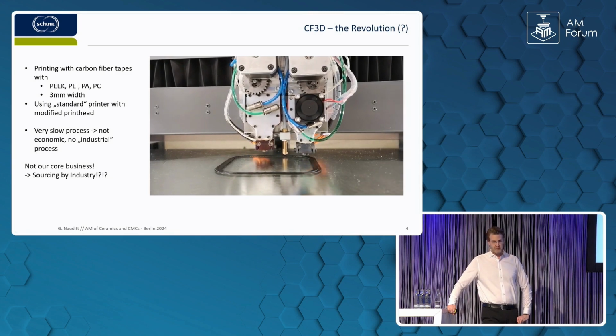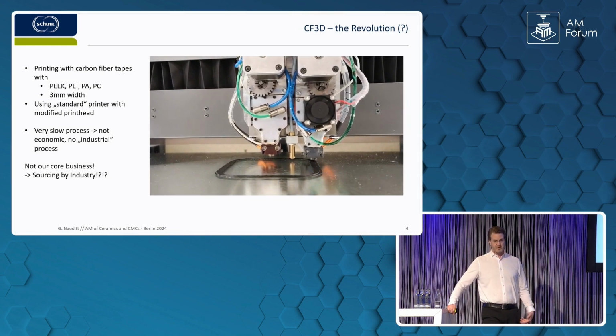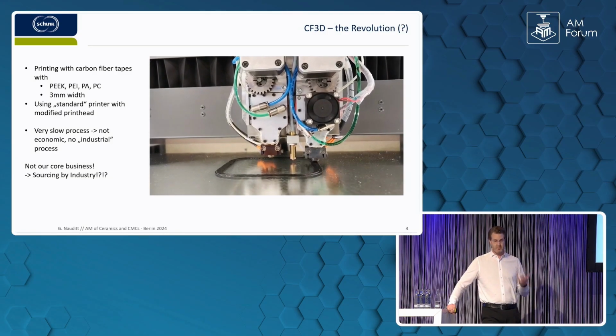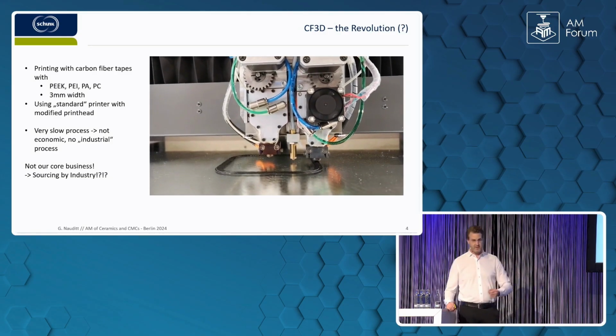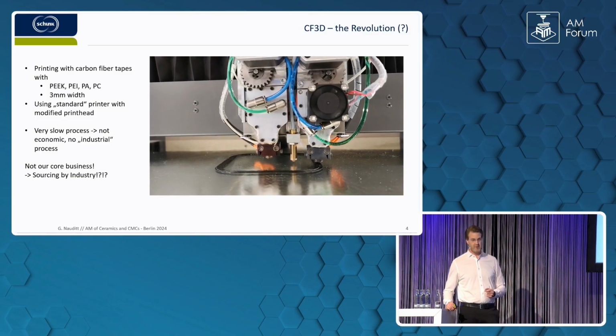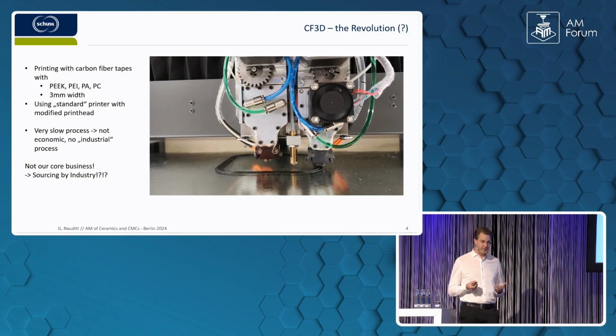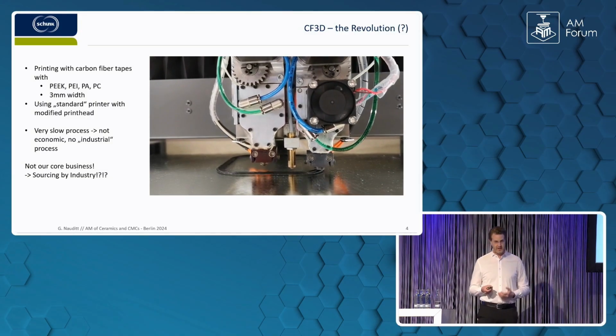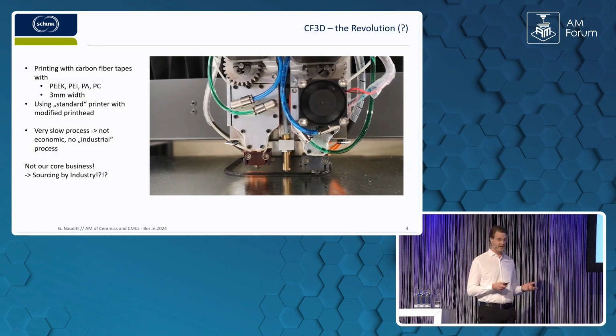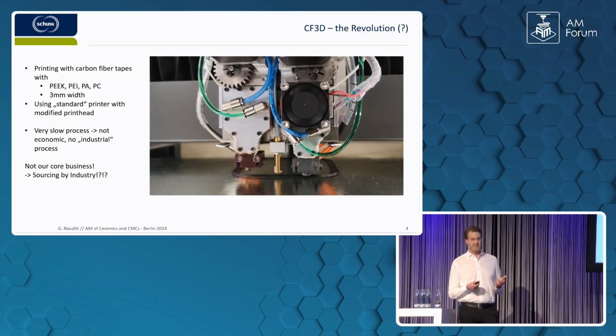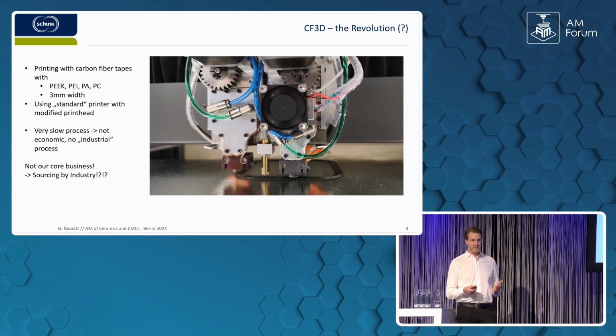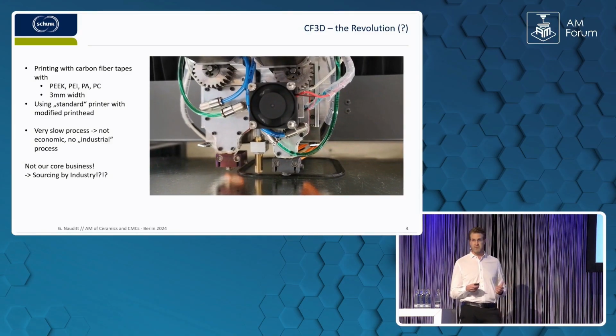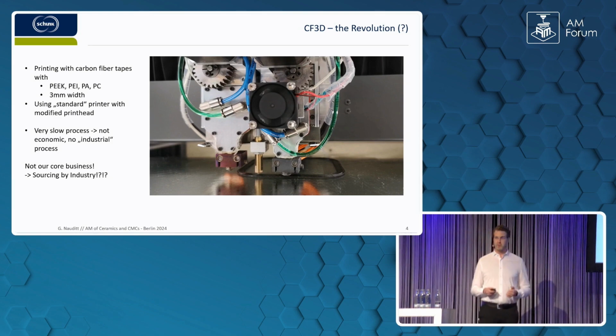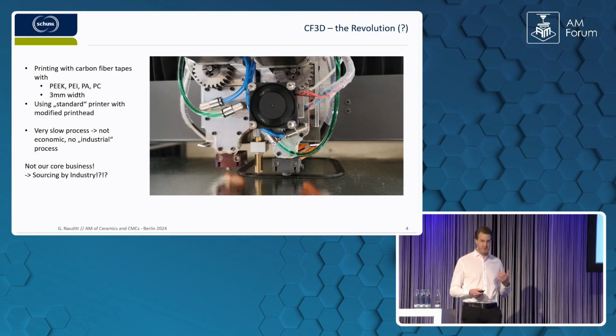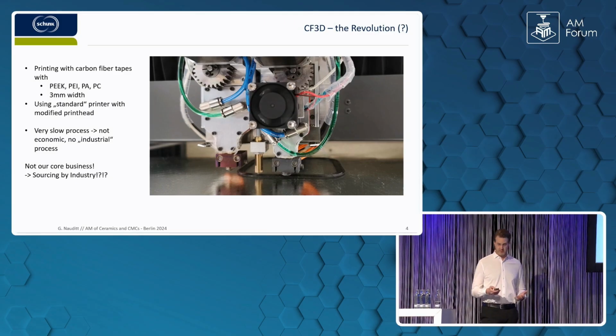There was a tool head developed which was able to extrude carbon fiber tapes, carbon fiber tape material. We printed, for example, here the carbon fiber PEEK material, and it worked. But we saw, and you're not looking at slow-mo here, you're looking at real time, it was slow, and we very fast encountered a lot of other problems where we said, okay, it was interesting, but maybe we should stop here. It's not our core business to create printers here. Maybe we should wait what the market will give us.